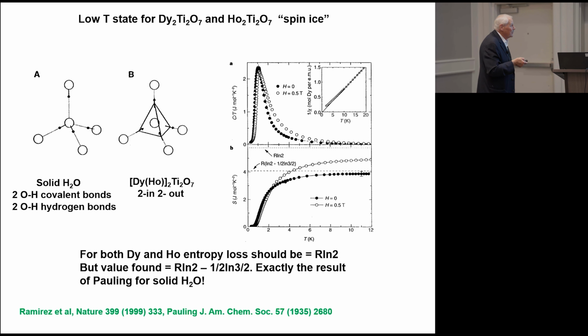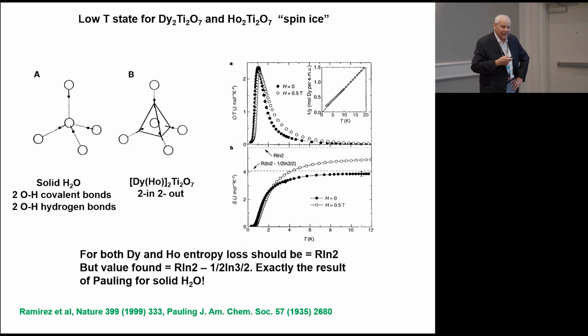One very famous implication of this is the following. You probably know about this. It's the so-called spin ice state. At low temperatures, dysprosium and holmium titanate fall into this spin ice state. It's called a spin ice state because it maps exactly onto water ice. Right? Here's water ice. Each oxygen atom in water ice has 2 covalent bonds and 2 hydrogen bonds, 2 in, 2 out. And that's exactly the same statistical situation as the 2-in 2-out model for holmium and dysprosium.